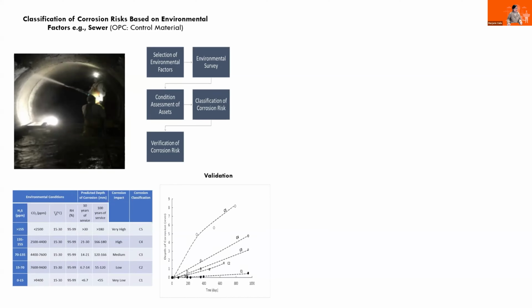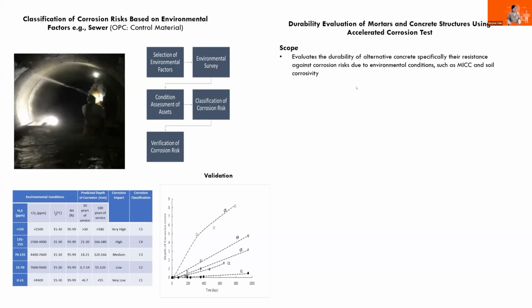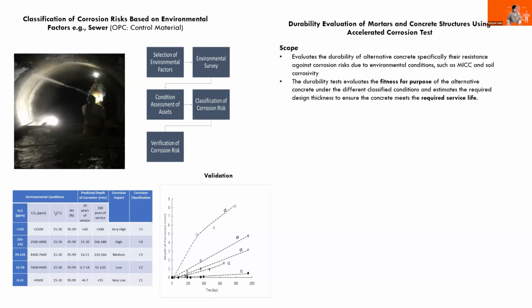So on the basis of that classification, what we have then done is try to propose a series of ways of validating the corrosivity of the different mortars. So this is a series of accelerated corrosion tests that essentially mimics the corrosion risk that is available in sewer. The scope of this test is to assess the durability of the different cementitious material as a function of those environmental conditions that could be a result of MICC and also soil corrosivity. The other aspect is that we do want to determine whether the materials themselves are fit for purpose. That means they will survive that environment, but also we wanted to understand the required service life of that material if it was actually applied in that environment.